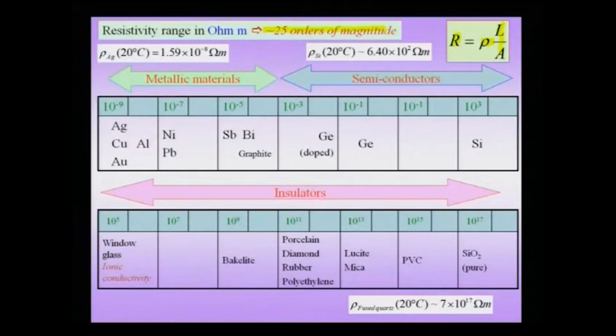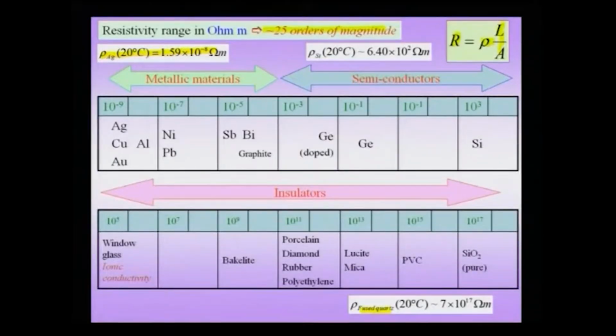On one hand, we have extremely good conductors with very low resistivities like silver, which at 20 degrees Celsius has a resistivity of the order of about 10 power minus 8 ohm meters. On the other hand, we have extremely high insulators like fused quartz, which at 20 degrees Celsius has a resistivity of the order of about 10 power 17 ohm meter.